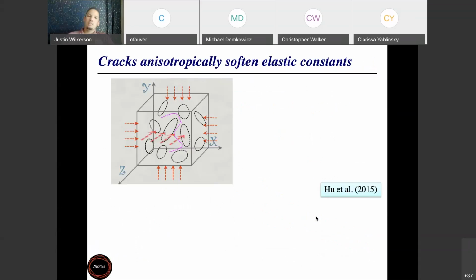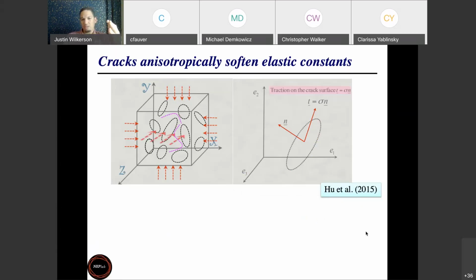For cracks, it's a little more complicated because the cracks have really well-defined orientations to them, like I mentioned, and that can introduce quite a bit of anisotropy that needs to be captured. One way that this is done quite well is in the model of Guangli Hu, which is published in JMPS in 2015. I'll refer you to that paper if you want some more details. Essentially, they consider multiple crack families in a material, and a crack family is any cracks that have the same orientation. This vector n denotes the orientation of a particular crack family.